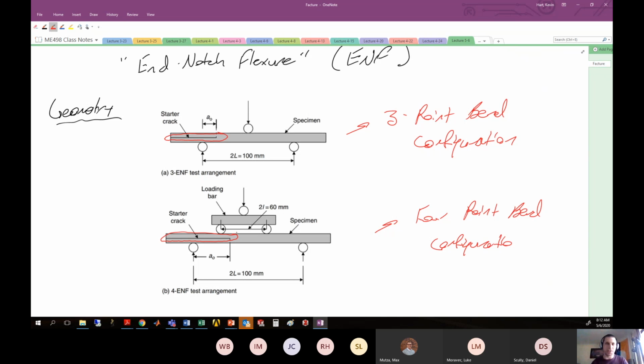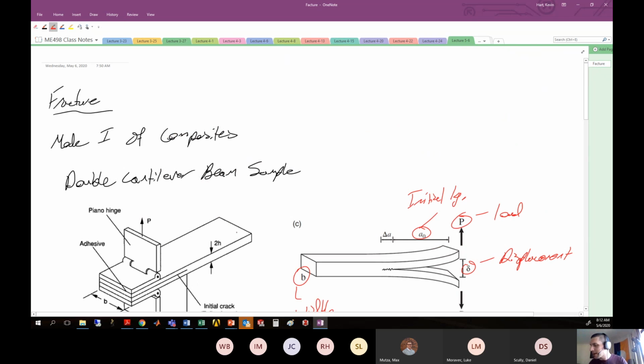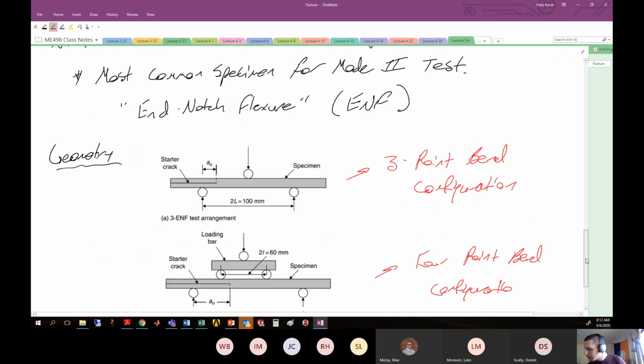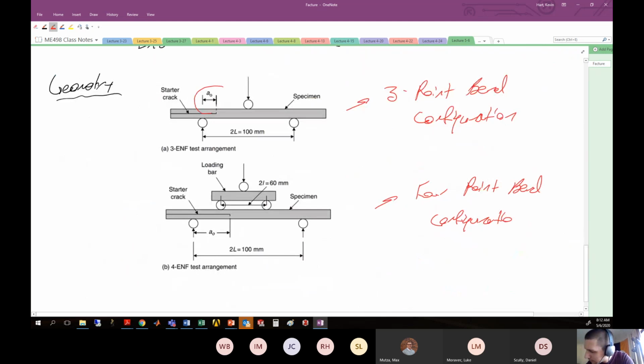All right, that starter crack is usually made by inserting a piece of Teflon or thin film during the manufacturing process of this particular laminate or woven structure, right? So you have that starter crack in there, and that initial crack length here is a sub zero. That initial crack length is the distance between the pin where this is loaded and the edge of the crack, all right? So here we have our loads. Here's P on 2, here's P on 2, and here's P, which is being applied to this particular specimen. All right, so what's going to happen here is just like the deck of cards example.